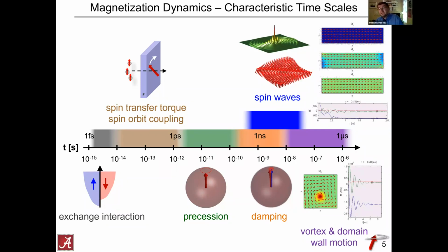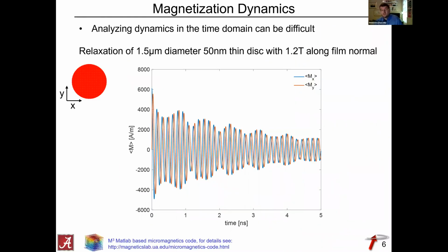All right, so that brings me to the actual time scales of this kind of dynamics. And here's an example that shows the average magnetization of a thin disk as a function of time, and this is actually a simulation of that disk, where the magnetization essentially realigns itself with an external field of 1.2 Tesla along the film normal.